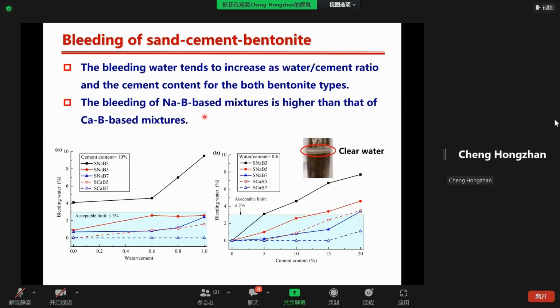Here is the bleeding result. The bleeding result shows that the bleeding water tends to increase as the water to cement ratio and the cement content increase for both bentonite types. By comparison, the bleeding of sodium bentonite mixtures was higher than calcium bentonite mixtures with the same bentonite content, because in the first stage for sodium bentonite mixtures, a higher water to sand ratio is selected. Additionally, addition of cement slurry causes more increase in the flowability and bleeding for sodium bentonite mixtures.